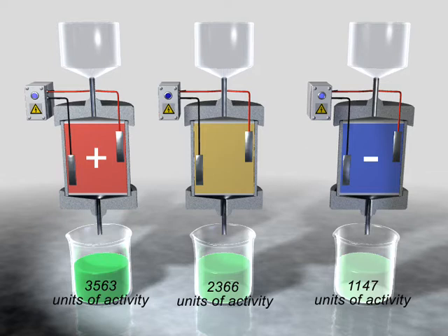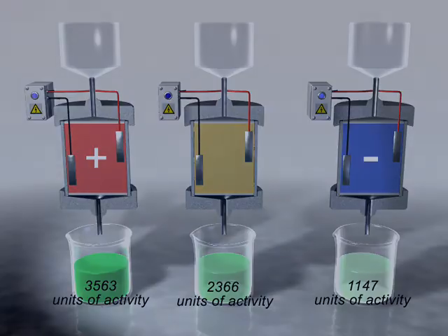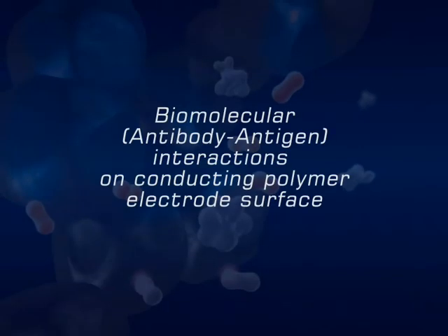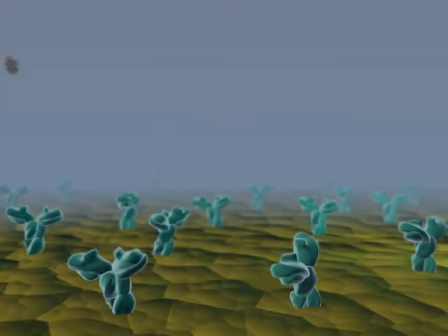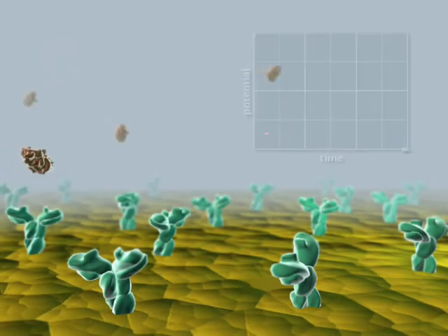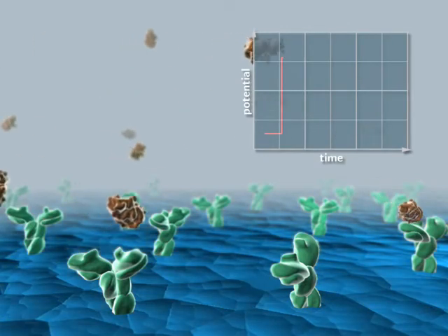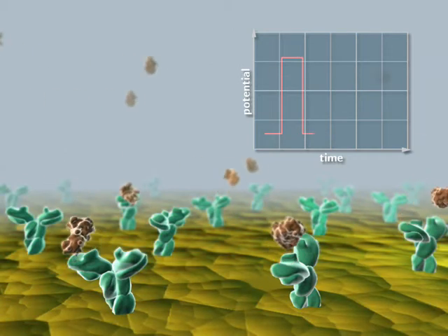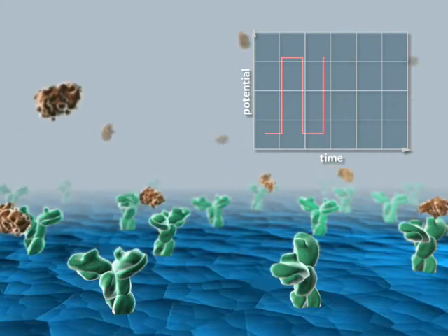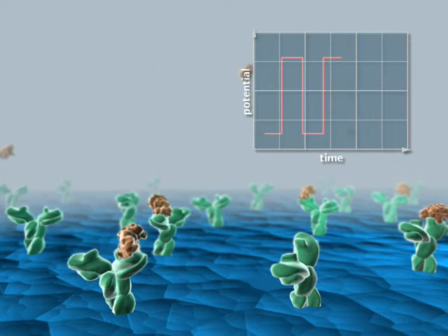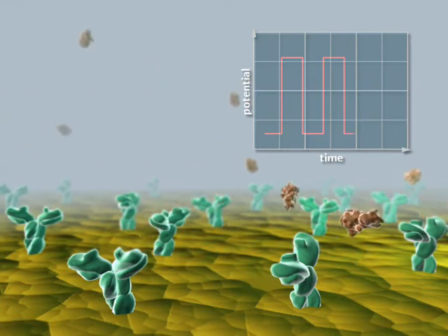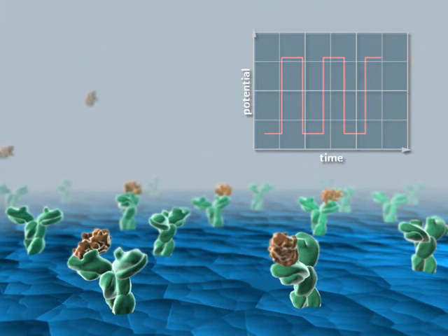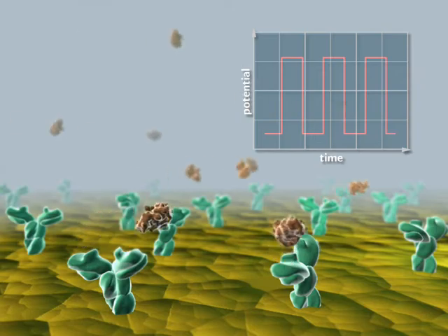with electrical stimulation. In subsequent experiments, we turned our attention to the control of antibody-antigen interactions on surfaces to be used for biosensing applications. Here, the antibody is incorporated into the conducting polymer at the point of synthesis. Now we use electrical stimulation to assist in antibody-antigen binding. We found that if the electrical impulse is reversed quickly enough, we can even effect a reversible protein binding interaction. This has subsequently been used for the development of a number of novel biosensing platforms.